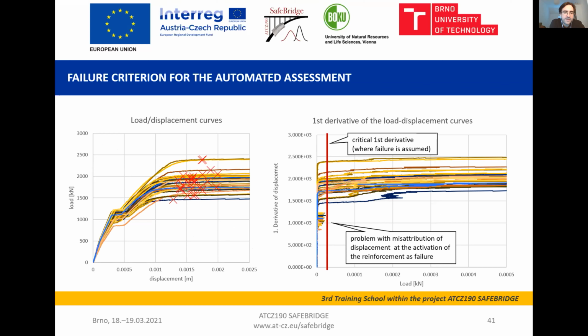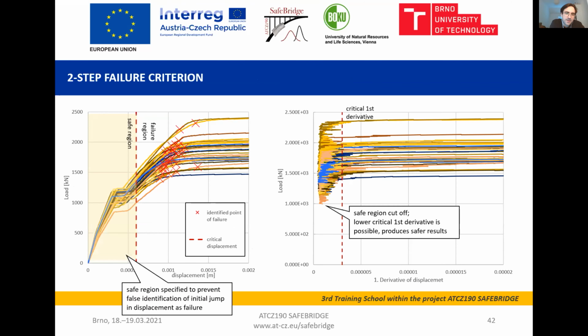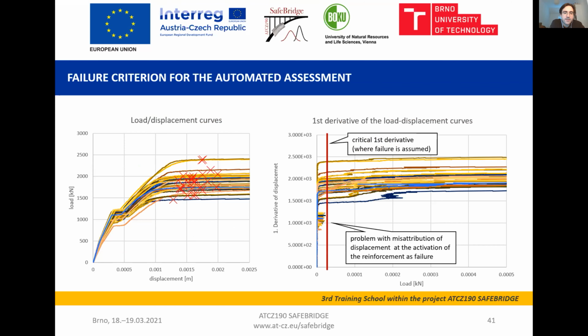Okay, so we can see on the left hand, one back. Yeah, we can see on the left hand the load displacement curves and the points of failure identified. On the right hand, we can see the first derivative of the load displacement curves. We can especially see pretty well this initial little jump in displacement where the reinforcement gets activated, and then later on when the actual failure sets in.